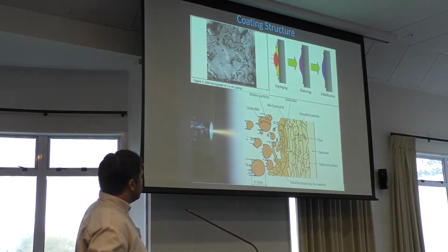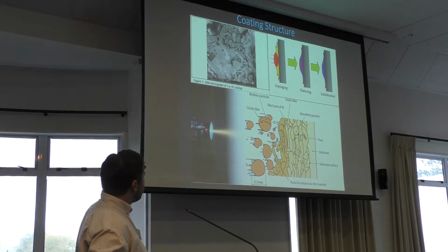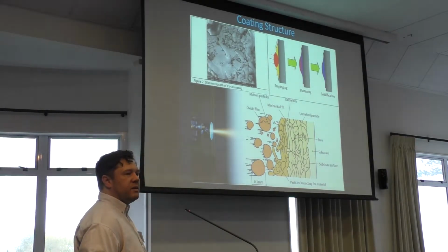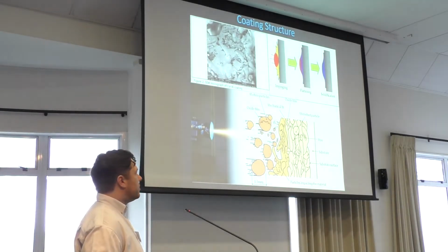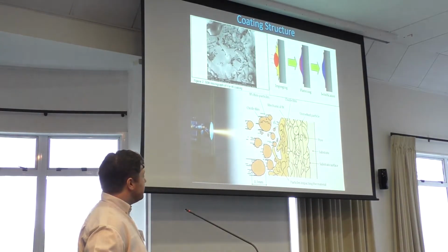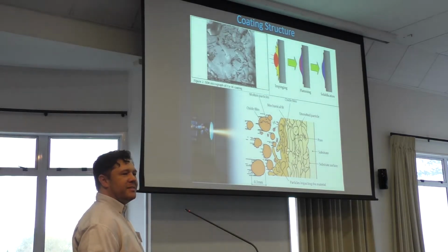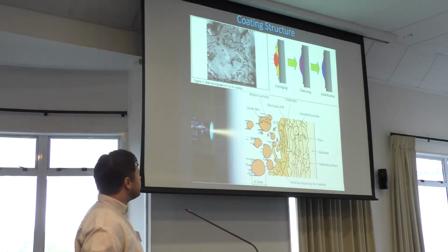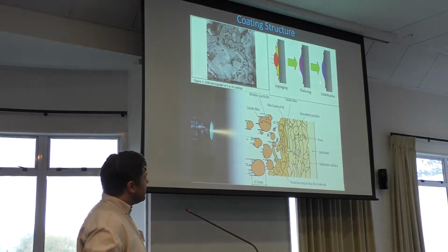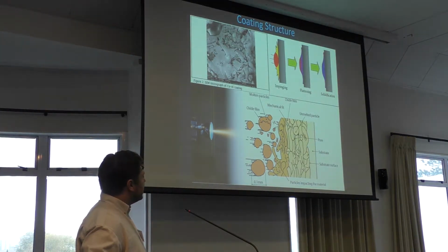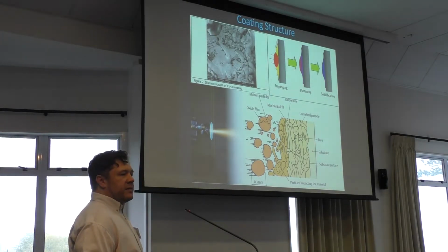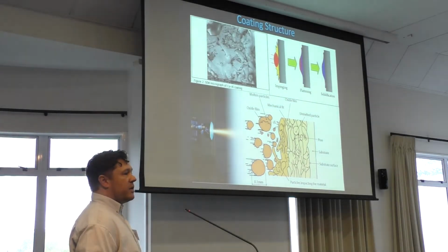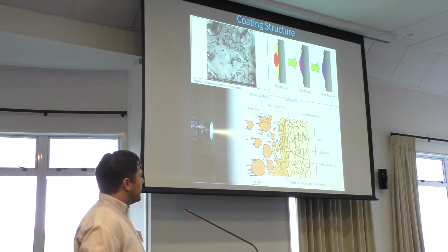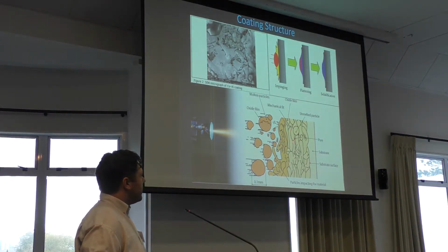But the coating is blown here, it's arced inside this nozzle, and then the compressed air comes behind it to atomise it, and we have all of these little particles. They all develop a small layer of oxide around the outside because they're using compressed air to blow them into the job, and then they go splat on the job. Literally, they call it splatology. There's a university terminology. So it just makes millions and millions of these little flattened pancakes that stack upon each other. Now, some of the particles are bigger than others and stay well moulded, and some of the particles aren't so big. So we get unmelted particles in the coating, and we get porosity in the coating.